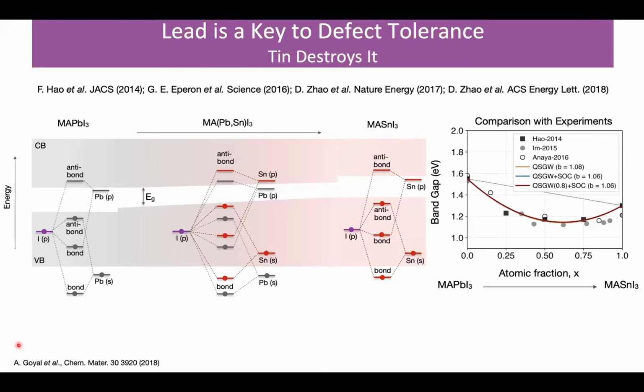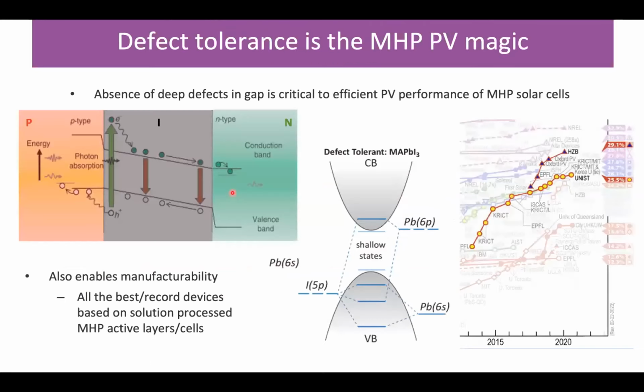And this is a diagram from a paper by some collaborators at NREL, where they calculate this and show how these bonding and anti-bonding sites are changed as you alloy in the tin, and it changes which orbitals are functionally governing the electronic gap in the system. We can use this as a nice tuning parameter, but we are destroying some of the defect tolerance as we do that, which is why lead is magic in the context of the solar perovskite materials. If it doesn't have lead, we tend to not think of it as a solar perovskite at NREL for the most part, which is something I'm happy to talk about. Lead is a great thing in the context of this.